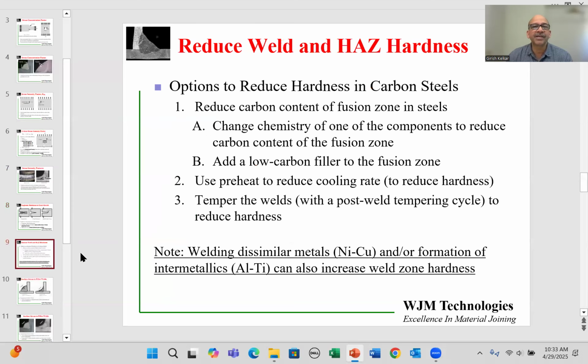So let's look at how we can reduce the hardness of the weld zone. Hardness is a very common issue in welding of steels. Now, this is true with other components as well, but the majority of the issues we come across are in the hardness of carbon steels. And the major reason for hardness in carbon steel is the carbon content. So one of the things we can do is to reduce the carbon content of the weld zone by changing one of the components to a lower carbon version of it, or we can add a low carbon filler. So we can introduce a filler alloy into the weld zone to reduce the hardness of the weld zone, so make it less susceptible to crack growth.